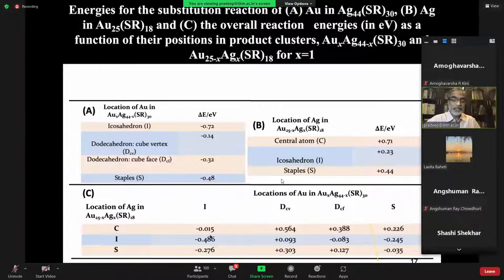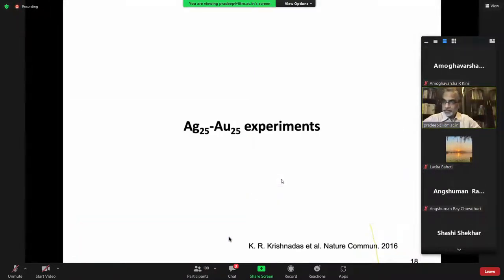Now you see that if you do that chemical reaction, the icosahedral position is negative, but these are all positive. Now, if I do, let us say, I position and then I position, that's again more negative, in fact. Others are, well, this is positive and others are negative. But the sum and substance of this is that I for I substitution is far more preferred than other substitution reactions. So chemistry is driven by enthalpy in this system. One can go on, but when you go to larger exchanges, you have isomeric combinations in the system, so computations become more involved.